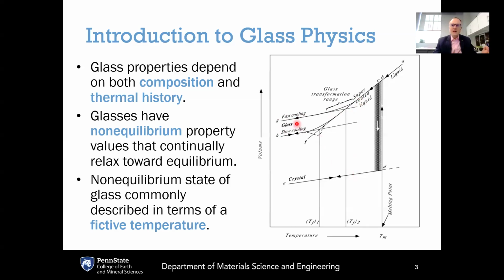Now, because glass is a non-equilibrium material, this means that the properties of the glass depend not just on its chemistry, and its current temperature and pressure, but the entire thermal history and, if applicable, the entire pressure history of the glass. For example, the two lines shown here show that a fast-cooled glass has a higher molar volume compared to a slow-cooled glass. That's because with a more slowly cooled glass, we've given it more time to stay in its metastable equilibrium, and then it falls out of equilibrium from the supercooled liquid at a lower temperature.